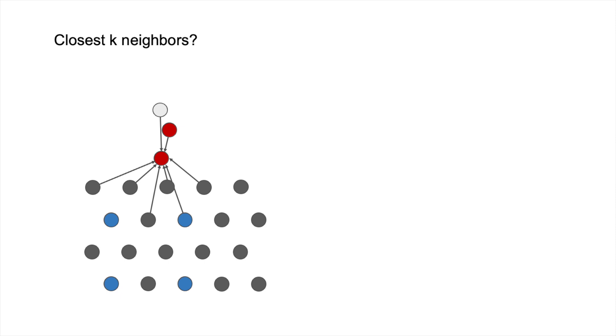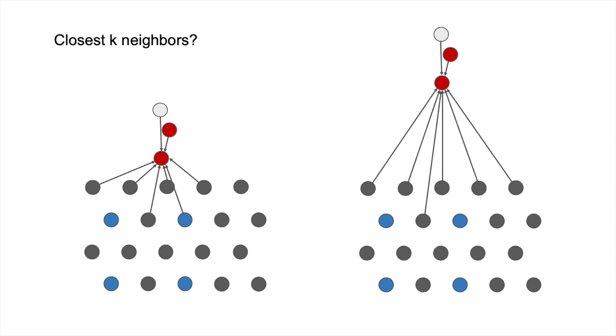Another possibility is we use a k closest neighbors. So just picking out k, let's say it's eight in this case, is going to be the eight closest neighbors or eight closest atoms to the atom of interest. And this allows us to solve the problem we just looked at. So if an adsorbate is too far away from the catalyst surface, beyond five angstroms, it's still going to include in its neighbor list some of the atoms from the catalyst itself. A lot of times what we do is a combination of both of these. So the atoms have to be within a fairly large cutoff radius, let's say 10 or 12 angstroms, and we pick at most, let's say, the 20 closest neighbors.